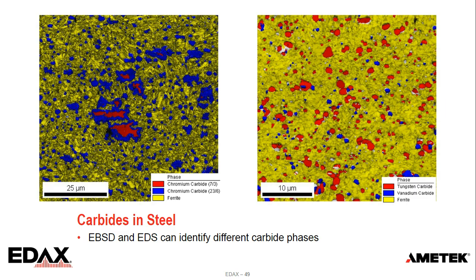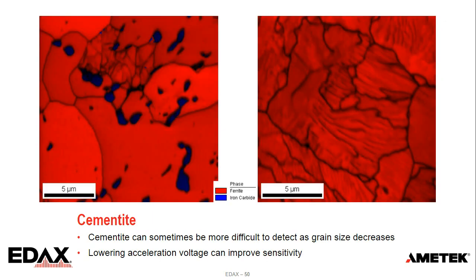So, you know, carbides, we can resolve those out nicely, but sometimes it's not always as easy. So this is just an example from cementite. The image on the left, kind of larger globular cementite, those come out nicely. On the right here, this shows more of a pearlitic microstructure, where the bands of iron carbide are much finer, much smaller, so it can be more difficult to detect, especially with larger step sizes. And there's been work that shows if you go to lower voltages, you can start to resolve that better. So you can get it, but sometimes it gets to be tricky, sometimes from a physics point of view, sometimes from a sampling point of view.